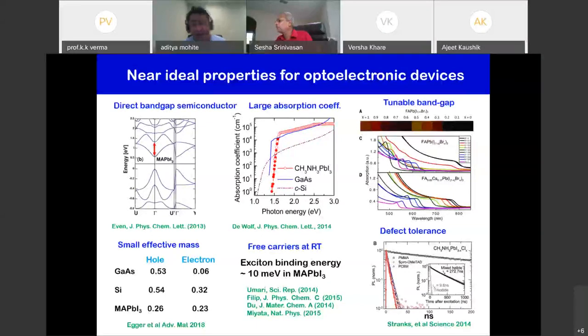And finally, another very unique and novel property of this perovskite is defect tolerance. What does that mean? There are of course defects like any other material. There are grain boundaries and different effects like this. But these defects don't seem to cause that much harm. These defects seem to be very close to your band edges, the conduction band and the valence band. And so you can get photoluminescence lifetimes which are very, very long, of the order of 200 nanoseconds, or people have even reported up to about a microsecond.